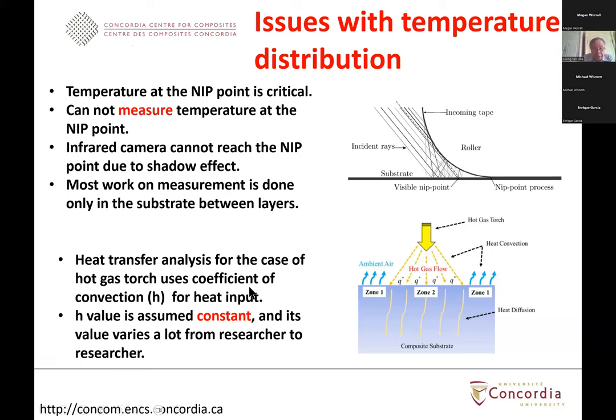From the analysis side, I refer to the case where you are using a hot gas torch. When people use a hot gas torch, you have some kind of heat input from the hot gas. In this case, people do the heat transfer analysis. And in order to get the input from the hot gas torch, they use the convective coefficient, the h value. And normally people assume this to be a constant. And even for the constant value, there is a lot of difference from one researcher to the next. The variation can sometimes be 100 times different. So there is a lot of inconsistency in the value that people assume. And besides that, this is not a constant. This varies from location to location.